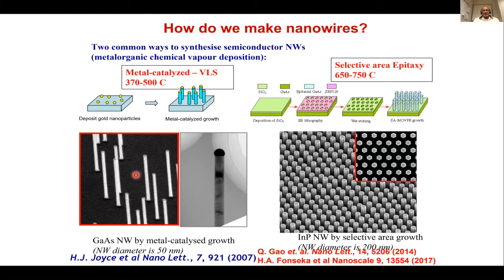We were able to show that you can get beautiful cylindrically shaped nanowires which are also atomically perfect. You can also create ordered patterns of nanowires using selective area epitaxy. In this case, we don't really use any metal nanoparticles, and we deposit some silicon dioxide by plasma enhanced chemical vapor deposition, put some photoresist, and do electron beam lithography to create patterns of holes. You transfer those patterns through the silicon dioxide so that you can expose indium phosphide, and then put this into the MOCVD reactor, heat it to somewhere between 650 to 750 degrees Celsius, and introduce the gases needed for the growth of indium phosphide, trimethyl indium and phosphine.